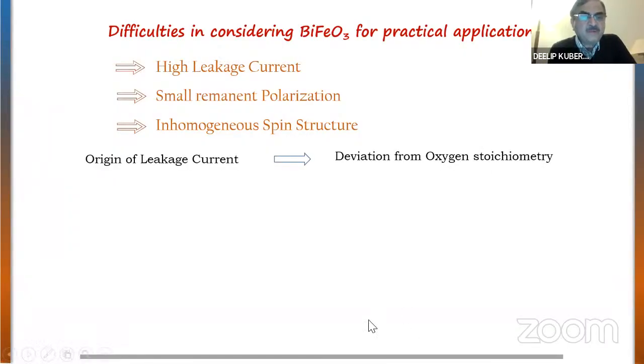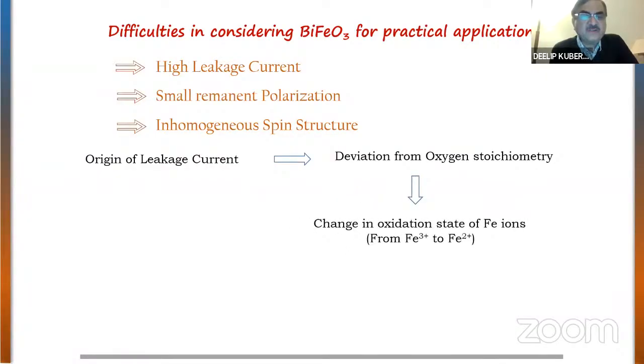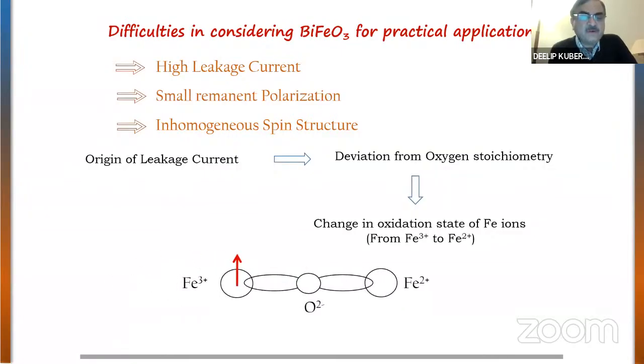So what happens now, these leakage currents, this is because of the deviation from the oxygen stoichiometry that leads to the origin of the leakage currents, basically, because there is a change in the oxidation state of Fe ions, Fe3+ to Fe2+ and so on. And because of that, this takes place via the oxygen.